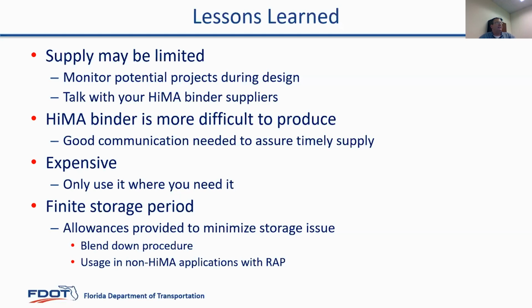So what we've done in our specs is we've made allowances if there's going to be storage issues. For instance, if it's been in your tank for a couple of weeks and now you've got bad weather coming and you're not going to be able to pave it, and you're going to get concerned. So we've got blend down procedures and also allowances to be used in non-HiMA applications, even with RAP, so that the contractor doesn't have to waste it somewhere. That's the last thing you want. So if you go to our specs, you'll see allowances so the contractor can get rid of it. We don't want this stuff hardened up in a tank.